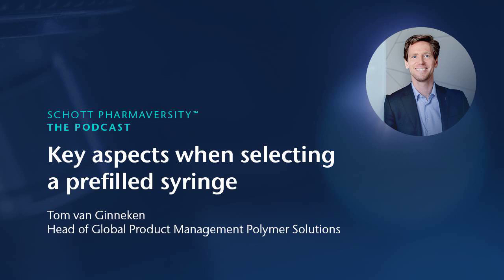And maybe to make it a little easier, I'll give some examples of certain applications that benefit more from a polymer. So the first one is aesthetic injections. Typically here we have a drug called hyaluronic acid, which is highly viscous, and which is used to reduce wrinkles in the face. And during the fill finishing process, one of the last steps is steam sterilization. And the combination of this steam sterilized product with the highly viscous drug and a really small needle, because you want to eliminate pain as much as possible when injecting into the face, means you need a lot of force to empty the syringe. And this can lead to needle pop-off or disconnection between the needle and the luer lock.